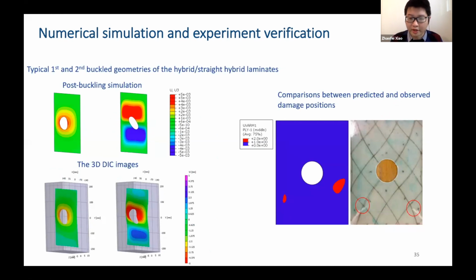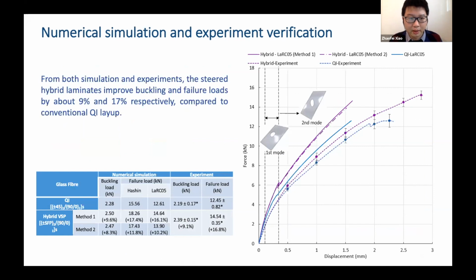between the simulation and the experiment, and the failure locations. So we can say we achieved a good agreement between the simulation and experiment. If we look at the actual data, we found both in the simulation and experiment, the steered hybrid laminates improved the buckling and failure load by about 9% and 17% respectively compared to the conventional QI layup. But if we look at the force and displacement curve on the right-hand side, we can still see the gradients are different between the simulation and the experimental data.